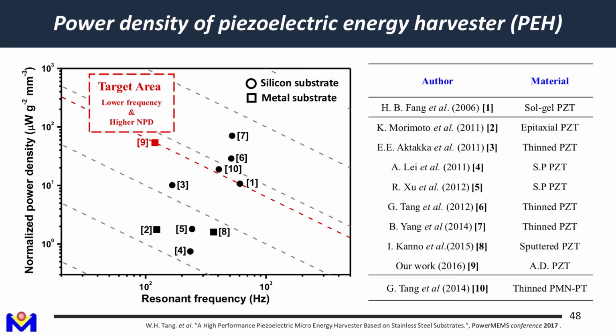And the horizontal axis is the resonance frequency. And the dashed line here is actually an iso-energy line. That means if you want to get the same amount of energy, if the resonance frequency is higher, although the normalized power density is low, in 1 second we get more cycles, so we get more energy. On the other end, on the same line, the resonance frequency is low, so cycles per second is lower, but the power density is higher, so we get the same amount of energy.